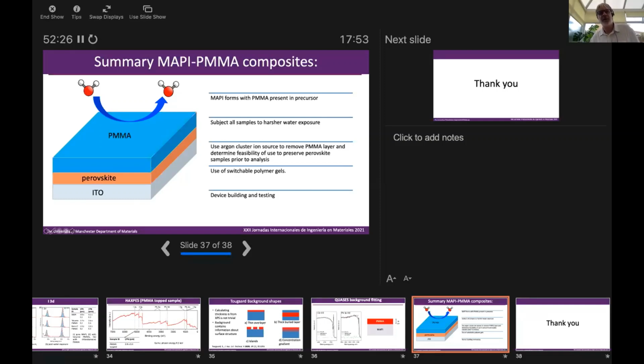We also want to go on to look at the use of switchable polymer gels. So we want to put the perovskite in a gel which is hydrophilic, and then use pH or temperature to switch it to a hydrophobic gel, so that we can put in the polar solvents and the polar ions of the perovskite precursor. Then once we heat it up to convert it, we want it to become hydrophobic to keep out the water. And we've just begun some device building and testing to see whether these encapsulated perovskites will actually function in a device.